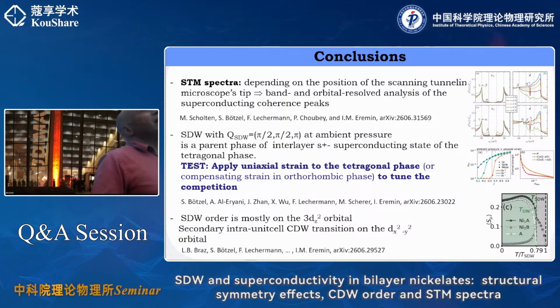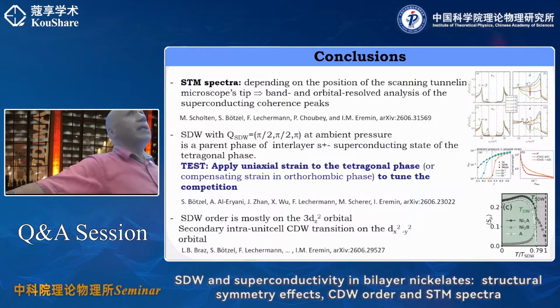So you really need to do the expansion. Right. It can have some accidental features. So I still believe that the physics is very similar. So you have a primary magnetic instability, and the charge density wave is a secondary instability, and it can also be viewed formally as a 2Q structure, except that in a trilayer it is a true 2Q structure, whereas in the bilayer, because the magnetic wave vector is commensurate, the 2Q builds a Q equal to 0 state.